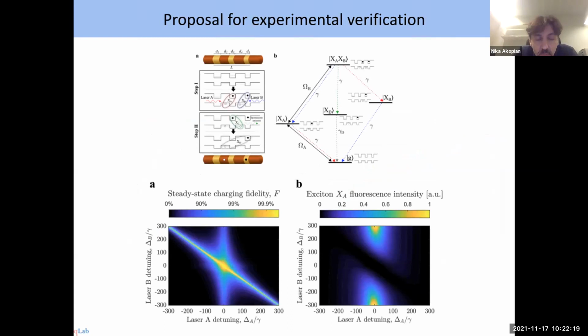So we not only want to create such an exciton, but also want to verify that the creation has been done successfully. How to do it? This is our proposal for how we will experimentally verify it. Usually in experiments you don't know the exact transition of this exciton. What we do in experiment is scan the laser around this transition and find the resonance, and scan the other laser around this transition and find the resonance. And when both lasers are in resonance, one here and one there, then the magic will happen. Then we can wait until this recombination happens and creates an electron here and a hole here.